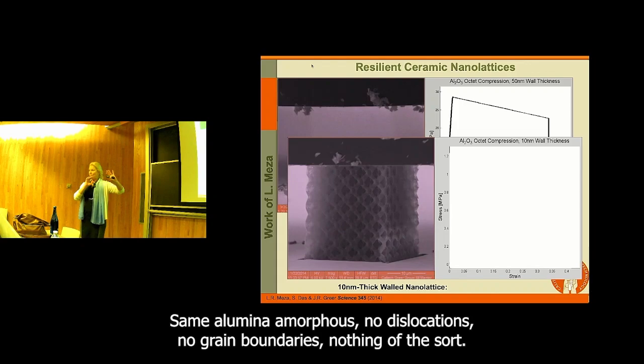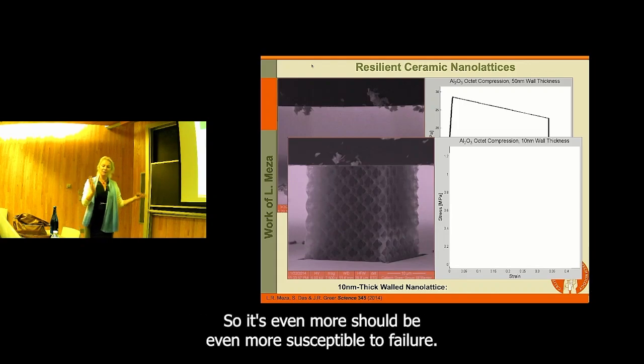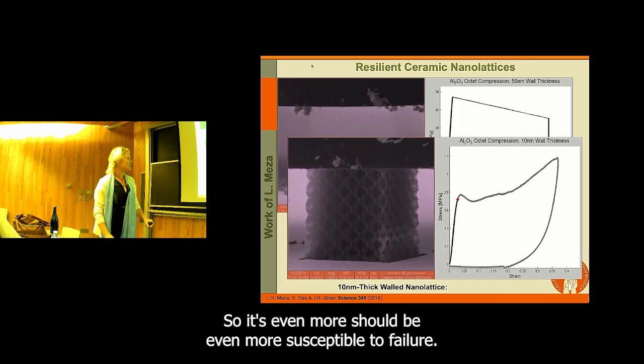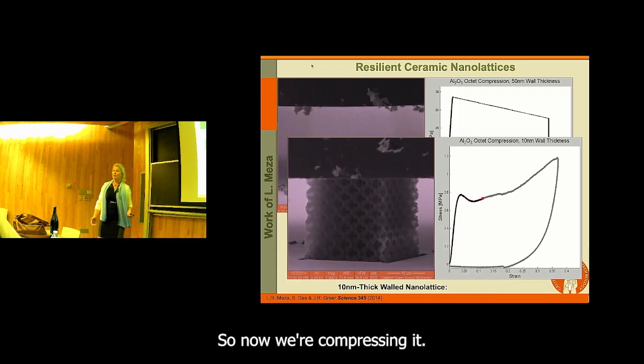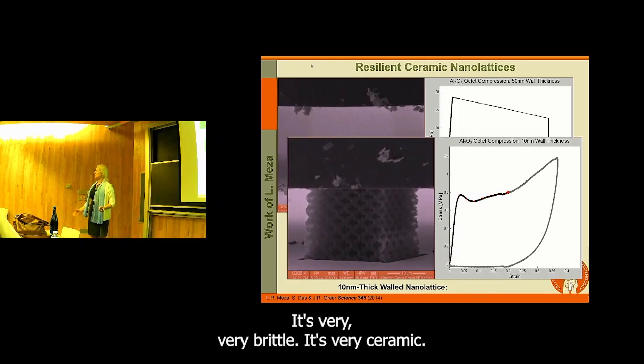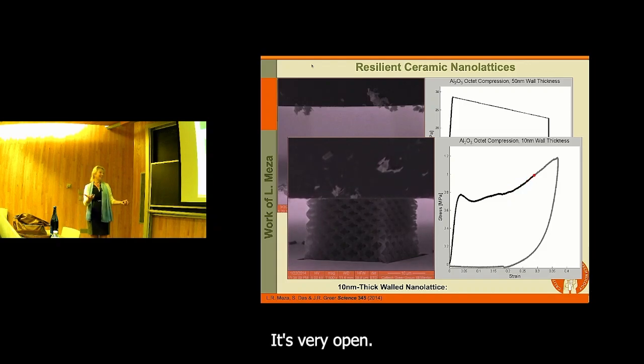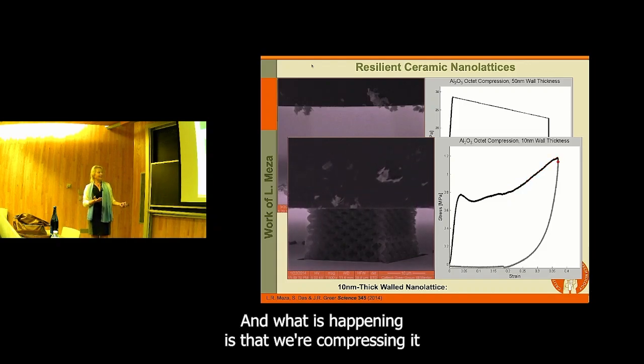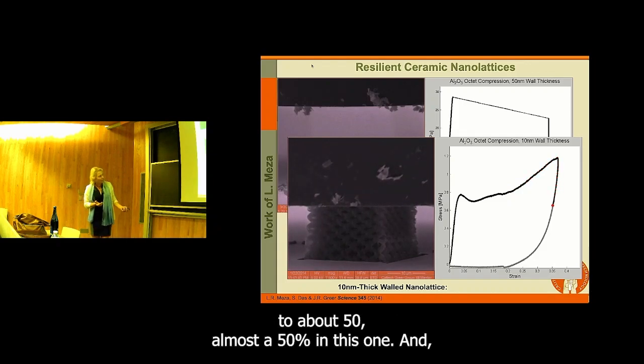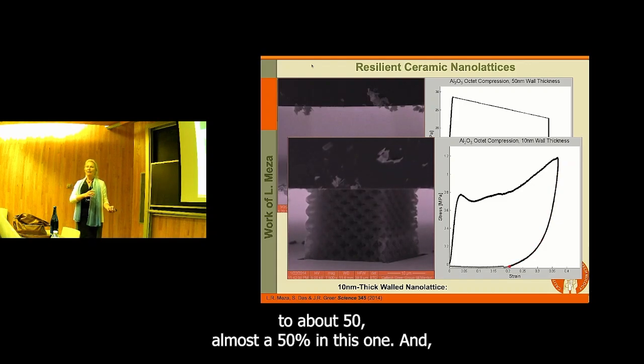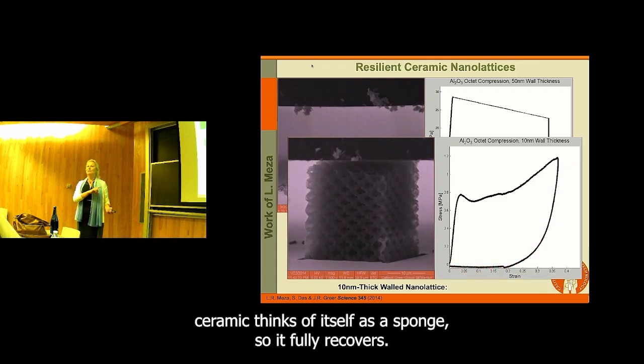Same alumina, amorphous, no dislocations, no grain boundaries, nothing of the sort. And we're going to compress it, so it should be even more susceptible to failure, right? So now we're compressing it. It's very, very brittle. It's very ceramic. It's very open. And what is happening is that we're compressing it almost to 50% in this one. And this particular ceramic thinks of itself as a sponge, so it fully recovers.